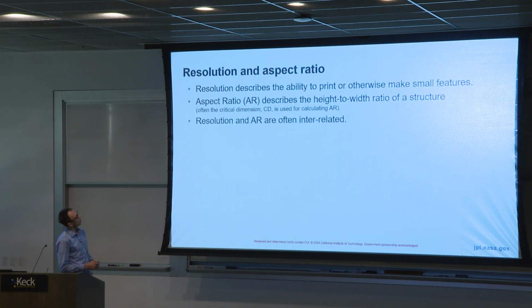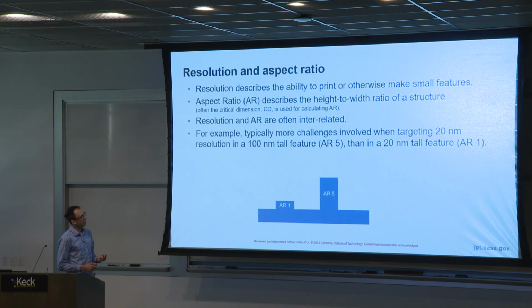My point here is that resolution and aspect ratio are tightly intertwined, in the sense that if someone stops me on the street and tells me, hey, I want to make a 20 nanometer feature, my first question back is going to be, okay, how tall is that feature? From this image here, if the feature you're hoping to make is 20 nanometers wide and only has to be 20 nanometers tall as well, your aspect ratio is 1, that's probably fine. If you tell me it needs to be 100 nanometers, now that's a little bit harder, might not be possible. But if you told me my aspect ratio needs to be 500, well, that's probably not going to work. So resolution coupled together with the aspect ratio is a very important thing to keep in mind when we're talking about what is possible to achieve when you're trying to make metasurfaces.